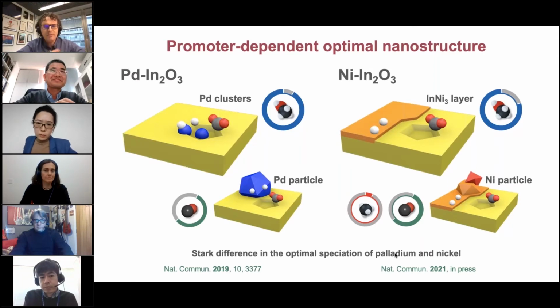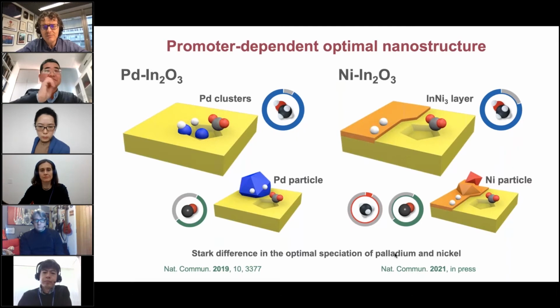Staying with CO2 hydrogenation, the strong dependence of the reaction on the promoter nanostructure is illustrated in this slide. As I said, palladium clusters on the left on indium oxide boost the rate of methanol production. However, if you start playing with nickel as an alternative promoter, which is a very close neighbor in the periodic table to palladium, a totally different nanostructure is required to maximize the methanol productivity. What you need to make in this case is not clusters, but ultra-thin indium-nickel alloys on top of indium oxide. As long as you are not able to control the ultra-thin indium-nickel alloy catalyst, because you have either very thick alloy particles or even nickel particles, you'll start producing undesired products like carbon monoxide or even worse, methane.